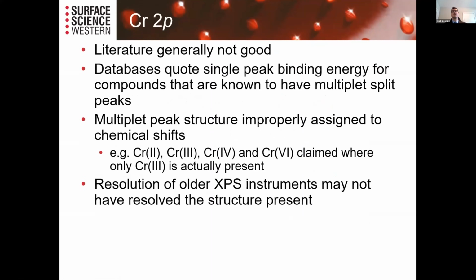For species with significant multiplet splitting, as I mentioned, we started with chromium, where the literature was generally not very good. We even had databases that were quoting single peak binding energies for compounds that were known to have multiplet split peaks. So, where do you pick that peak? And again, the multiplet peak structure was improperly assigned to various chemical shifts. Some of the issue may have been resolution of older XPS instruments, but mostly it was just that people didn't understand that these phenomena were occurring within these spectra.